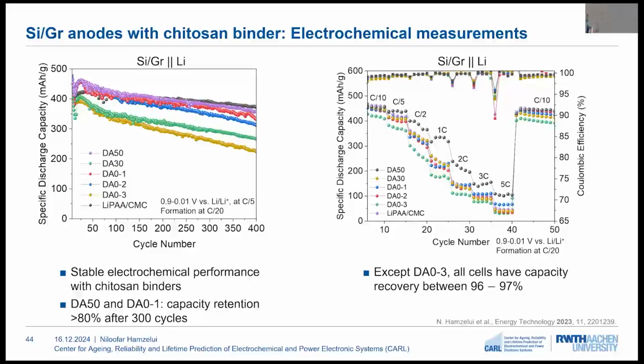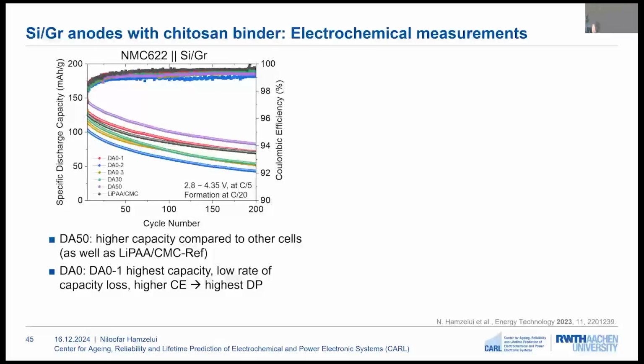Then the rate capability measurements were performed on the electrodes, and here we can see that except one of the chitosan binders, the others all show a capacity recovery in the range of 96 to 97%. The electrodes were assembled in a full cell against NMC622 cathode, and again, the electrochemical performance of the electrodes was investigated. And here we can see that the cell having chitosan with DA50 shows a higher capacity compared to all the other electrodes, also compared to the reference electrode with lithium polyacrylic acid and CMC binder.